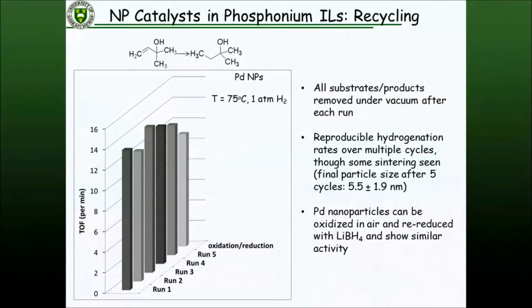You can recycle these systems really well because these are non-volatile liquids. It's very easy to pump off the products at the end of the reaction. The catalyst stays behind in the ionic liquid. And so we've been able to do the same reaction over and over again. In the case of palladium nanoparticles for this particular allylic alcohol hydrogenation, we do see over time that the particle size goes from about 2.5 nanometers to about 5.5 nanometers after 5 cycles. So there is a little bit of sintering going on with nanoparticles. They're getting a little bit larger as we do more and more catalysis.